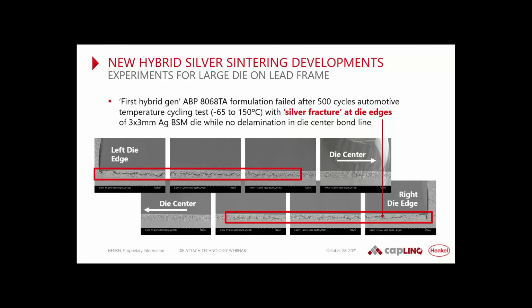But okay, I think this is for small die, successful, widely used. But then how about bigger dies? And of course, here we're still looking for the holy grail. I think you can imagine the bigger the die, the bigger the stresses are over the die from the center to the edge. And what happens here, you see some nice cross sections of the first gen material, TA, comparable to TB. Basically, it failed 500 cycles automotive on, in this case, a 3x3 millimeter die at the edges. And here you see the crack from the edges, where the stress is the highest, going inside.